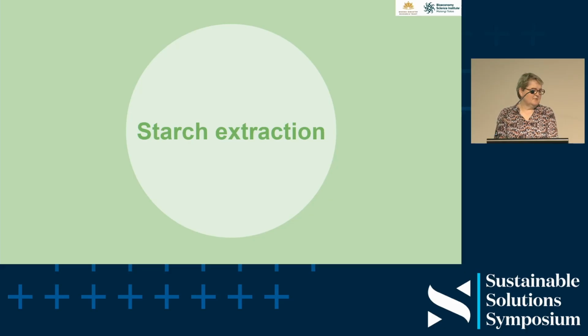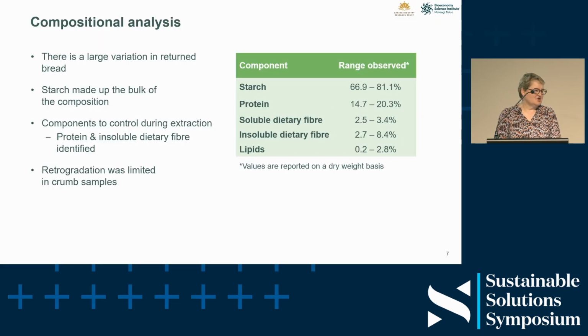So the first thing that we looked at, with the royal we, obviously the researchers were doing the work, was starch extraction. And we looked at the compositional analysis of the bread waste. Okay, so key things here is that there's a large variation in the returned bread. You'll see there that the starch composition was from 67 up to 81%, so it's good to know that there is a large amount of starch in the waste, as that was what we needed to make the thermoplastic starch. There is some protein, 14.7 to 20.3%.